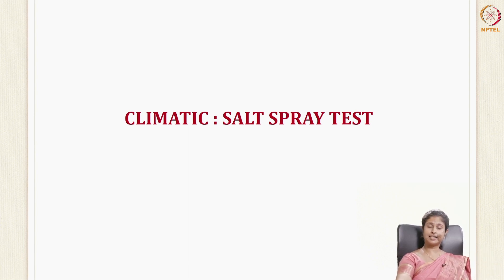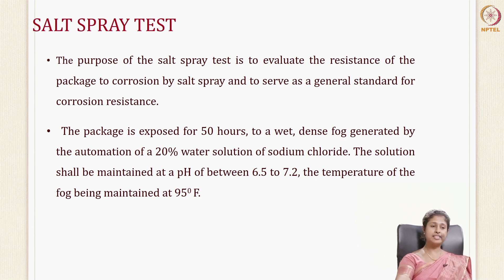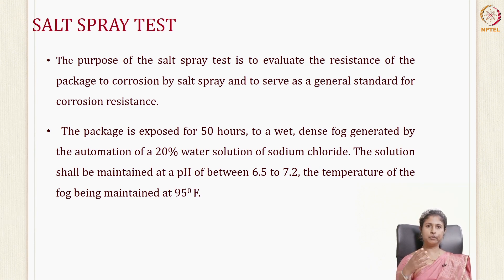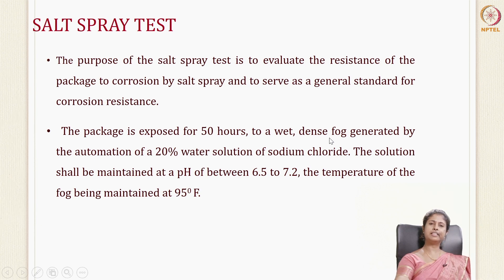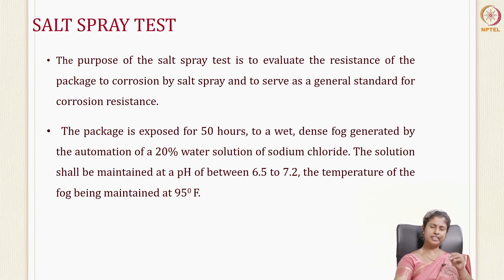The third climatic test is the salt spray test. A package would encounter salt spray naturally during shipment. The purpose is to evaluate the resistance of the package to corrosion by salt spray and to serve as a general standard for corrosion resistance. The package is exposed for 50 hours to a wet dense fog generated by atomization of water containing 20% sodium chloride, sprayed onto the packages. The solution is maintained at a pH of 6.5 to 7.2 and a temperature of 95 degrees Fahrenheit. This reveals any corrosion, color change, or other effects where the salt contacts the package surface.